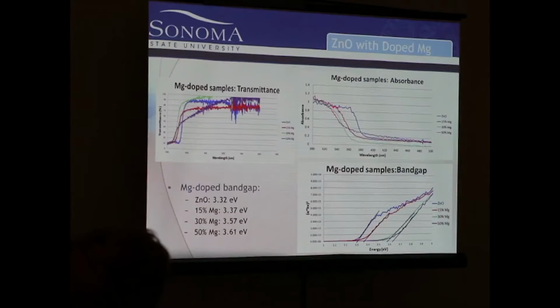Then 15%, this red line, we can see it's slightly shifted in the absorbance, but it starts at the same place and has generally the same slope. And then 30% has a nicer slope and actually goes to zero a lot faster, which is something that we also liked. And then 50%, once again, it was a little too much, so the quality of our line was not desirable. And so through all this information, we can calculate the band gap, and that's also another important component.